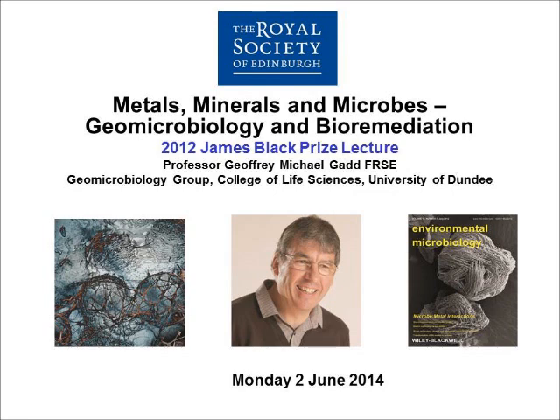There's very, very thin layers. It's a layered mineral. You can split it apart. It gives very flat, thin layers, so you can use it like a microscope cover slip and expose it to organisms or bury it and things like this. And quite easily you can see fungal footprints where organisms have etched the surface, they've dissolved. There's some physical things perhaps as they grow along, roughing up the surface, a zone perhaps where there's exudates and things dissolving. And this kind of system makes it quite easy to show effects of the organisms on minerals. And of course, in that case, you can quite easily confirm a role for fungi in formation of clay minerals.